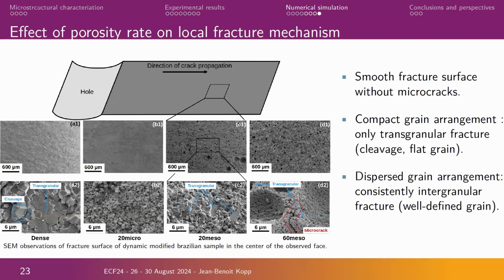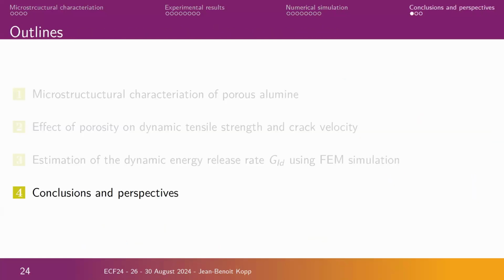And we have observed the fracture surface just near the middle of the specimen, in the smooth part of the fracture surface in the dynamic regime, which is quasi-permanent. So in this quasi-permanent regime, we do not observe any microcracks in the volume and only smooth fracture surface with the same local mechanism at the grain scale with transgranular and intergranular mechanism.